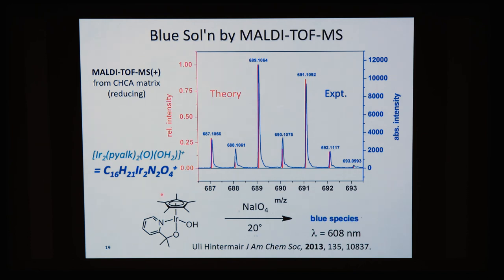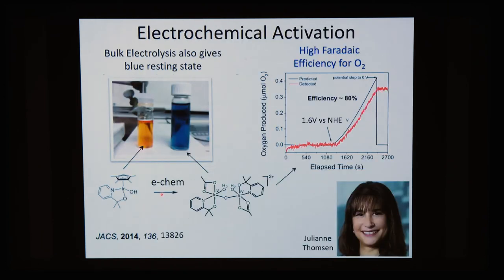And the blue solution was also looked at by MALDI-TOF mass spec. And the core of the molecule survives the mass spec experiment and gives an isotope pattern which is consistent with the expected core structure. Now, Julie was able to show electrochemical activation, and bulk electrolysis also gives the same resting state.